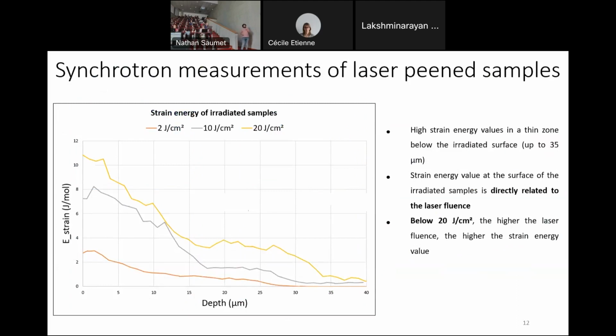And here are some results from synchrotron measurements. And so here is represented the strain energy stored in the material as a function of the depth below the irradiated surface. So here for 3 different values, 2, 10 and 20 joule per centimeter square, we can see the evolution, which is quite linear as a function of the fluence. And we can see that this stored energy decreases in the depth of the material because of the decreasing of the shock wave, which is relevant with the simulations. And we can see that the higher the fluence is, the higher the stored energy is.